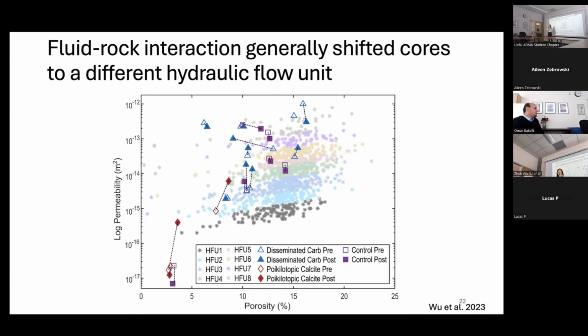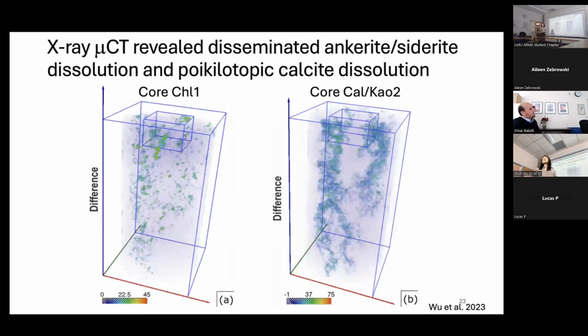So when iron carbonate dissolves or iron-containing clay dissolves, immediately after they dissolve, which I'll show you later, they tend to reprecipitate iron oxide, like hematite. So those minerals actually refill some of the pores. And we think that's the reason you might see the porosity decrease, because not only does dissolution happen, reprecipitation happens immediately after, for which there is evidence as well, which I will show you later.